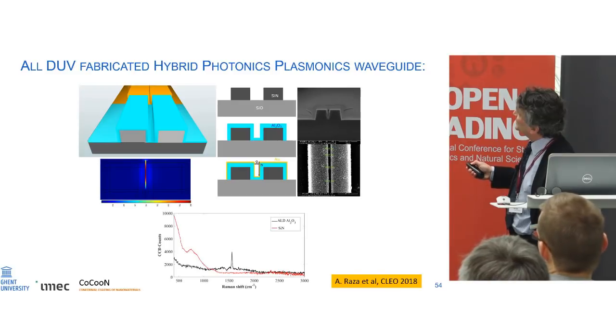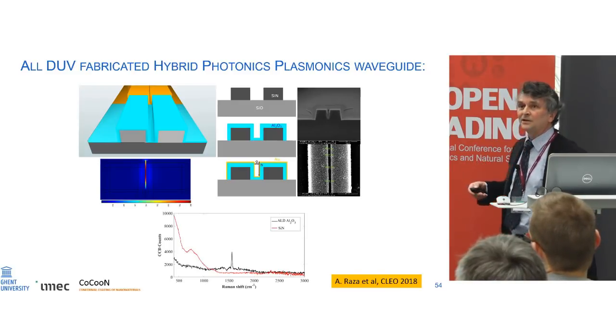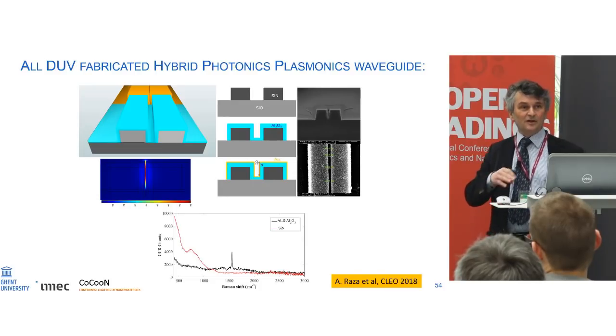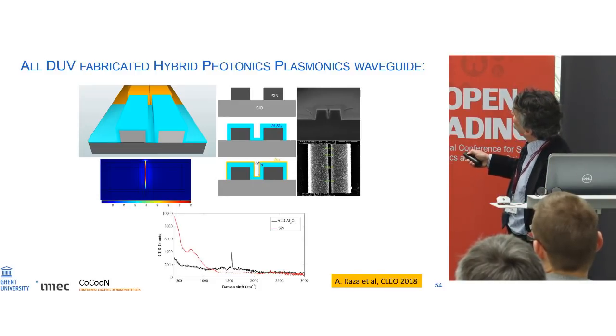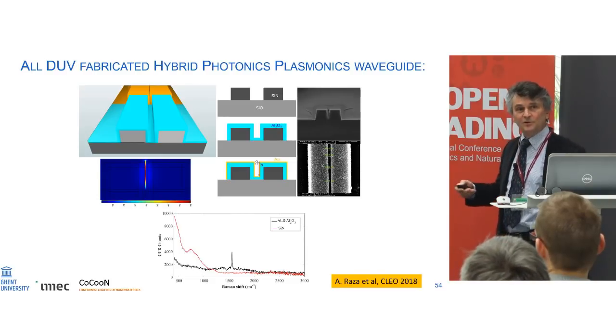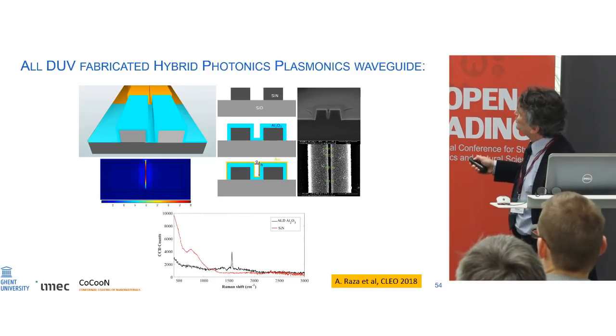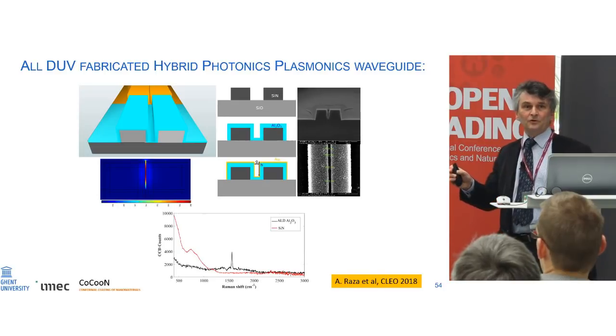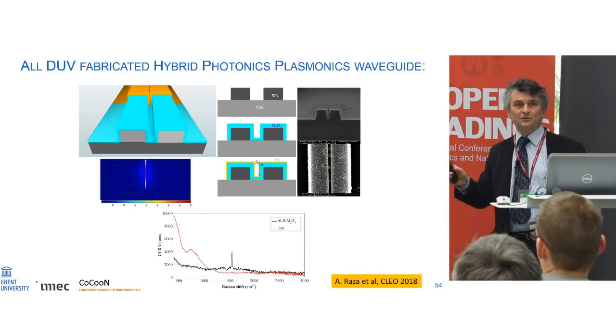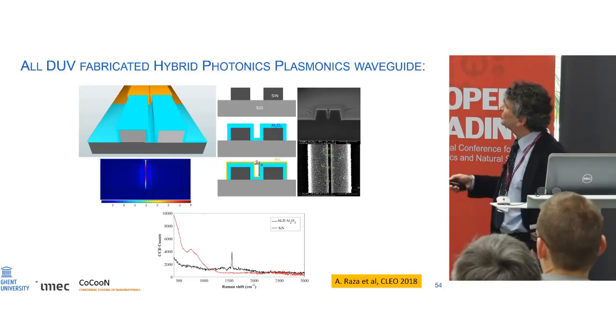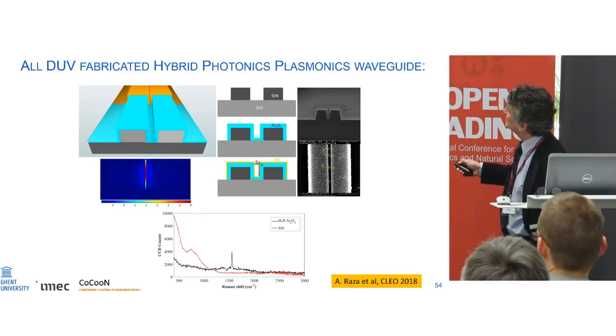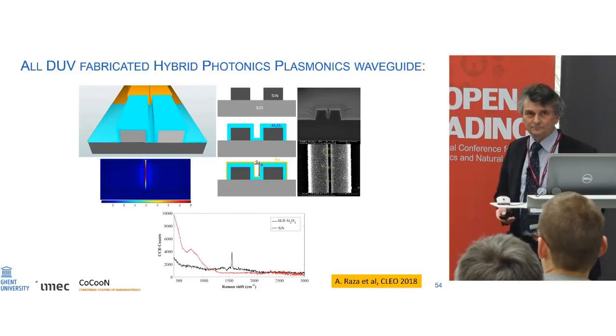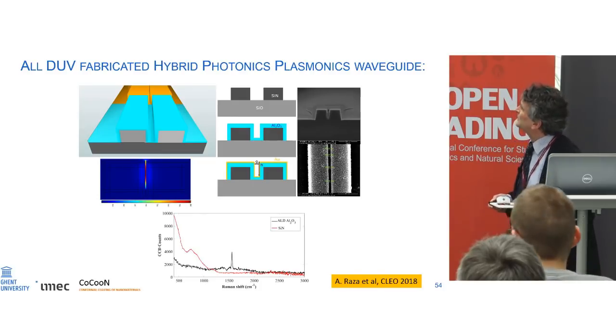Then we apply layers by means of atomic layer deposition, and atomic layer deposition, ALD, is conformal, so we can coat this structure with a layer of, in this case, alumina, and the thickness here and the thickness on the sidewalls is equal because of the conformality. So basically, we can narrow down at will the slot from its value of, say, 150 nanometer all the way down to, say, 40 nanometer or so, and then we coat with a thin gold layer, and we now have created a gold metal slot of, say, 20 or 30 nanometer wide in a very easy procedure.